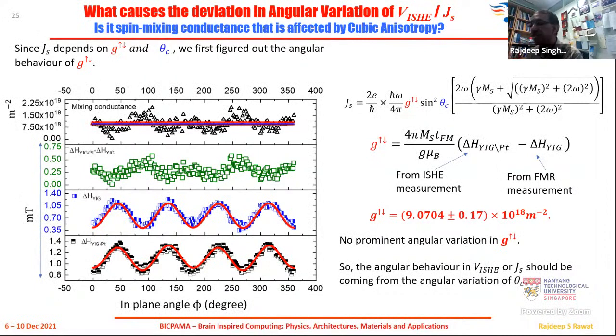But then we also wanted to see which properties of the material are affected by this cubic anisotropy of 0, 0, 1. Because if you look at this VISHE voltage, which I mentioned, that is basically controlled by the spin current Js. And if you look at the expression for the spin current Js, it depends majorly on two factors, the spin mixing conductance and the precession cone angle. So spin mixing conductance is a property which comes into the picture when you have an interface. In our case, the interface is between the ferromagnet and the non-magnetic layer.